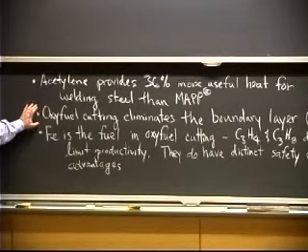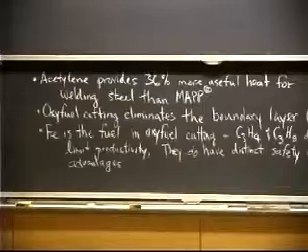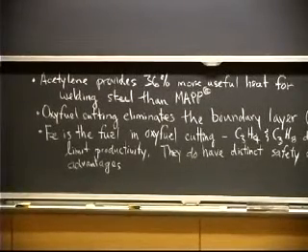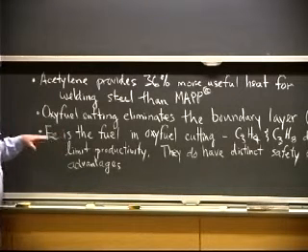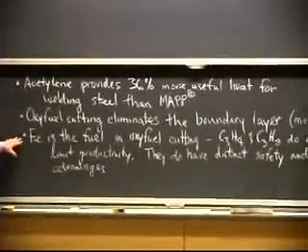We also mentioned oxyacetylene cutting, and how the cutting eliminates the boundary layer. Essentially the gas that you're blowing in there would ordinarily be the boundary layer, but in this case the oxygen is reacting with the iron and condensing to form a liquid oxide. And so there is no gas boundary layer. You're essentially creating a vacuum, if you will, at that spot. And I put "mostly" down because in a few minutes I'm going to show you where there is some contamination and how that contamination actually does produce a partial boundary layer, which slows down the process.